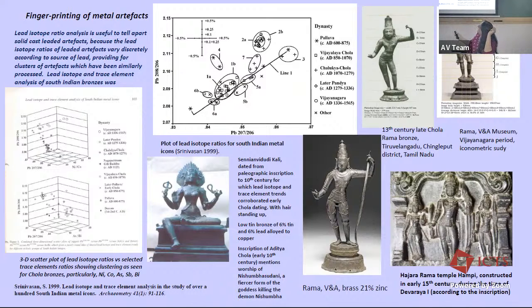And one thing that seems very clear, for example, is that the Chola bronzes seem to all cluster up here, and the Vijayanagara bronzes of a later period tend to cluster up there. So this kind of clustering is also useful, at least for making stylistic comparisons. And on the basis of that, for instance, I could reassess some bronzes which had been thought to be Chola as to whether they were actually Chola or Vijayanagara and vice versa.